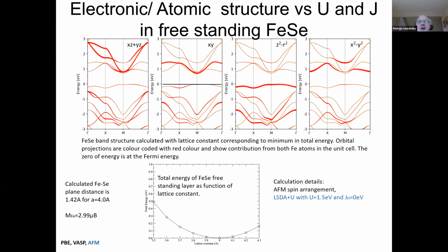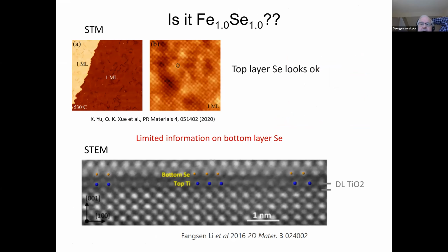So the non-magnetic, if you had this kind of lattice constant, the selenium would be much closer to the iron plane in the non-magnetic material. But actually, the distance now is 1.42 angstroms, which is much larger than, for example, if you use a Poisson-like ratio to determine what that distance is, it would be more like 1.30 or 1.28 angstroms. Okay, so again, magnetism, larger magnetic moment gives you this very huge change in the selenium to iron plane distance.